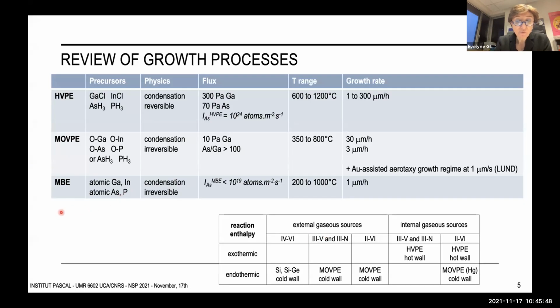When comparing the 3 current epitaxial techniques, of course, they were all designed for condensation, but we now use them to implement solidification through VLS growth. The main difference is that condensation is easily reversible when using chloride precursors. HVPE makes use of very high material inputs, high material fluxes, and this is something that we have to keep in mind when we analyze the growth properties, especially for nanowire growth by VLS, where the supersaturation of the elements will be very high in the catalyst droplets.